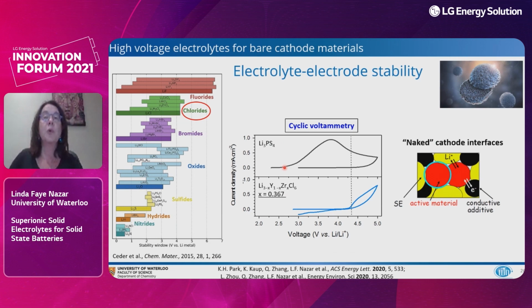Now, this is, as I said, the worst case scenario because we're mixing a lot of conductive carbon with a halide to push it to the limit, but we can actually get to voltages higher than that. And the important thing is that now we don't need to worry about trying to place electronically insulating layers like lithium niobate on the surface. We can now use a naked cathode interface and achieve much easier processing and also better performance of these materials in solid state cells. And so that's what I'll end off my talk by describing.